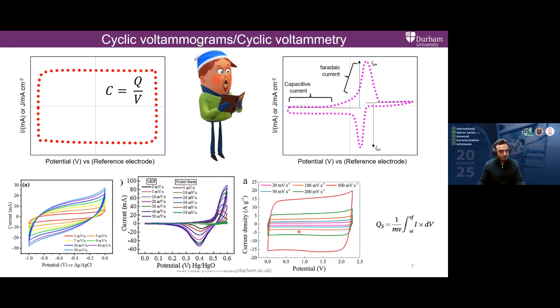And the third example I've presented here is actually the potential V. So you can see there is a clear difference between these two. Whenever you are seeing a cyclic voltammogram, and if a potential is shown rather than the potential versus Hg/HgO, that clearly means that the testing was carried out in 2 electrode rather than in 3 electrode. If someone is not mentioning Ag/AgCl in 3 electrode, I think it will be misleading, because you are contradicting your results or the way of presenting results with the 3 electrode assembly.